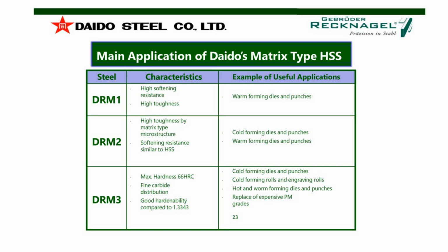And they moved from PM grades to DRM3. They use the same layer, the same PVD coating. And I get a lot of feedback from my customers that DRM3 with the same hardness of 66 HRC, with the same layer, is working in the same way as powder steel grades. This is outstanding. And with DRM3, if you want to replace a powder steel grade, you will save a lot of money because DRM3 is much cheaper than a powder steel grade.